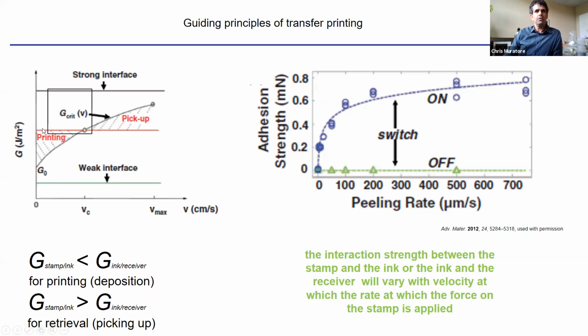And so when I want to pick up the material, I want it to stick to the surface. And so I can control this velocity at which I deform the stamp. And when I want to detach the thing I picked up and put it on the substrate, then I want to operate at a different deformation velocity, right? So I can do this simple energy balance depending on what I want to do. If I want to deposit the ink onto the receiver or the substrate, then I need to make sure that I've got the right kind of adhesive energy from the ink that I want to print. So again, by changing the rate of deformation of these stamps, I can control whether I'm picking up or dropping off material from the surface of that stamp.